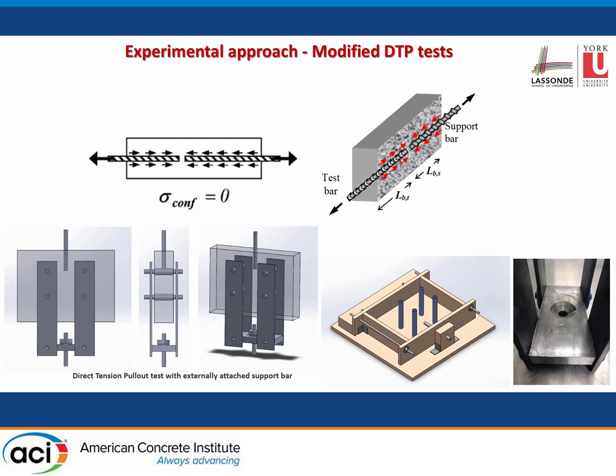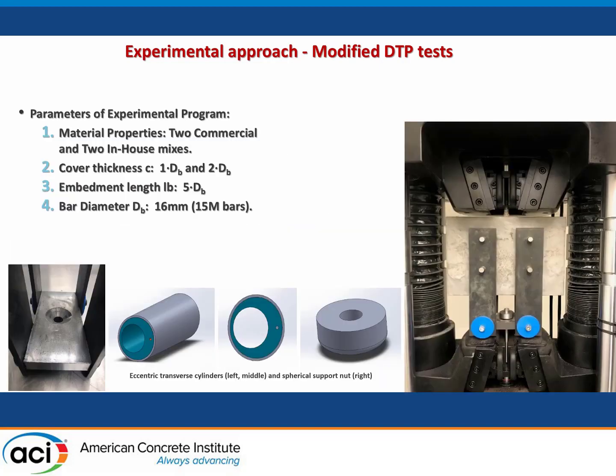And the concrete block is held down through a hardware device that has been fabricated with a hinge at the bottom. The test bar is being pulled upwards in order to test the development capacity of a short anchorage length, which is only 5 dB, based on some analysis that we did, so that we are able to say that the force developed by the bar divided by the contact area gives us a good feeling of the local bond strength. So this is the test specimen mounted on the MTS test frame. The various hardware that we made for adjustment of the specimen are shown to the left.